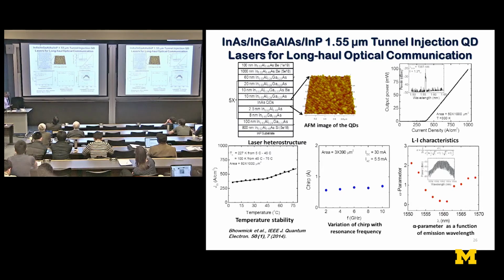And we got, again, beautiful results, very low alpha factors and chirp, and again, extreme temperature stability. I might add that the commercial 1.55 micron lasers made out of indium gallium arsenide phosphide quantum wells have T0 values of about 40 Kelvin. So this is what has now put these lasers in the market, and there's one company, Ranovus in Germany, that's marketing now all the 1.55 micron quantum dot lasers.